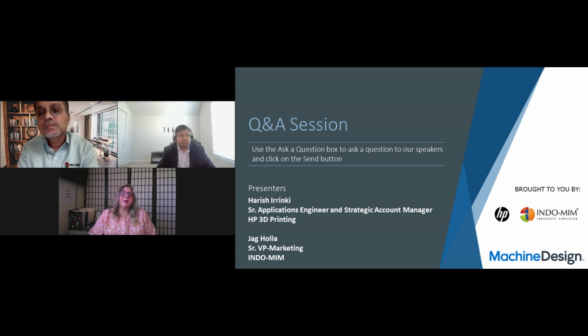Okay, so how long did it take for HP and INDO-MIM to collaboratively develop a new material and scale production for these parts? For M2, correct me if I'm wrong, Harish, it took probably around 6 to 7 months since we decided to adopt M2 on the HP platform. That's correct. Since it's our first material for collaboration, it took us a little more time to fine tune to the INDO-MIM process, and for INDO-MIM to fine tune their material and sintering to our printing technology. But the new material, 316L stainless steel, which will be announced at Formnext, took us almost 45 to 60 days.